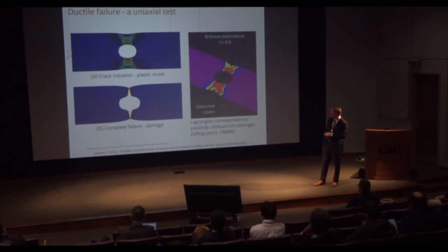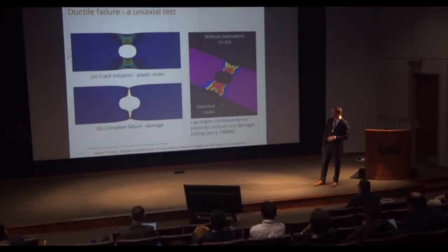The nice thing about this kind of bond-associated model is that you're not tracking damage at a node and then distributing it to all the bonds in some uniform way. Every bond has its own state variable that's tracked, and you get very clean fractures, clean unzipping. There's no mass loss like you get in classical theory where you're using damage mechanics and then maybe element deletion or something like that.